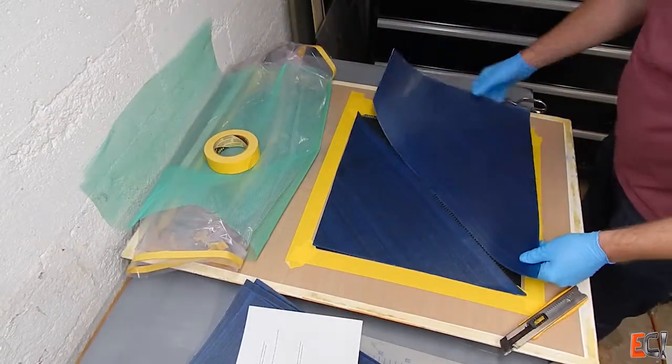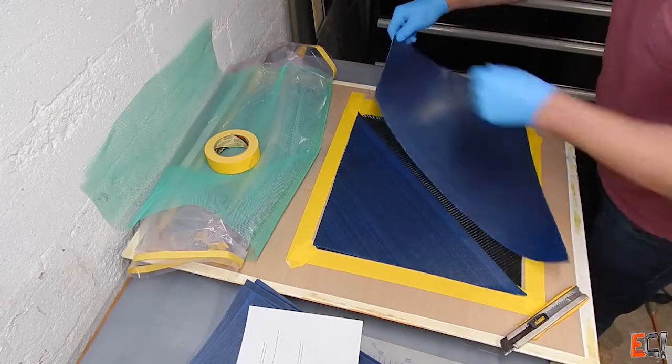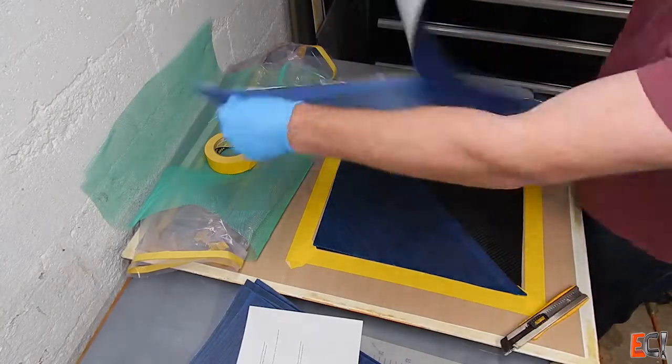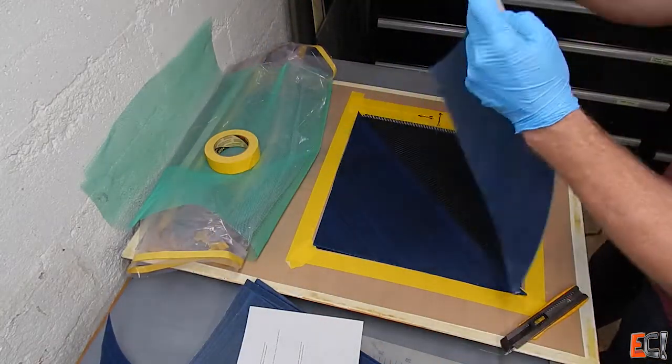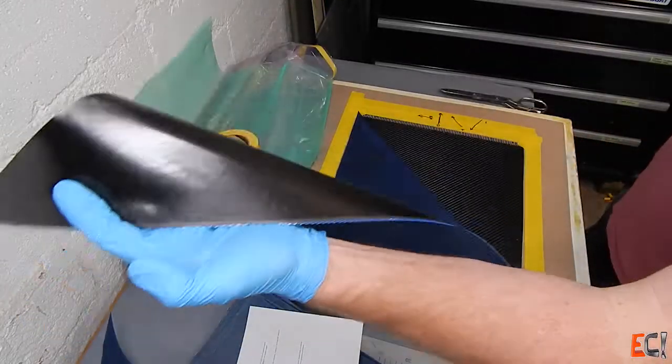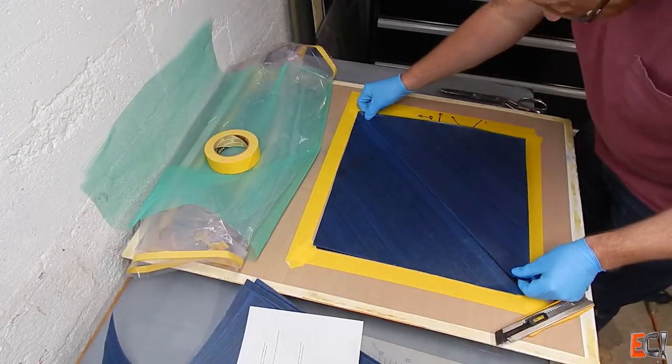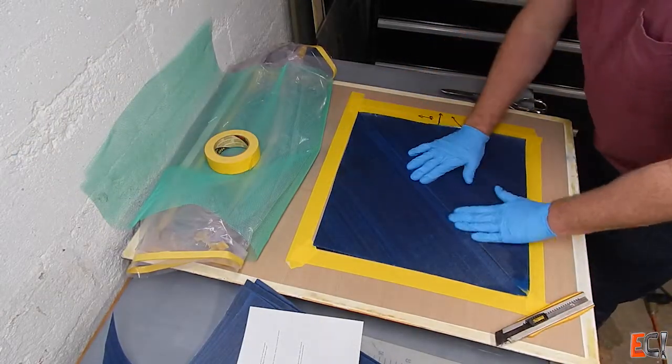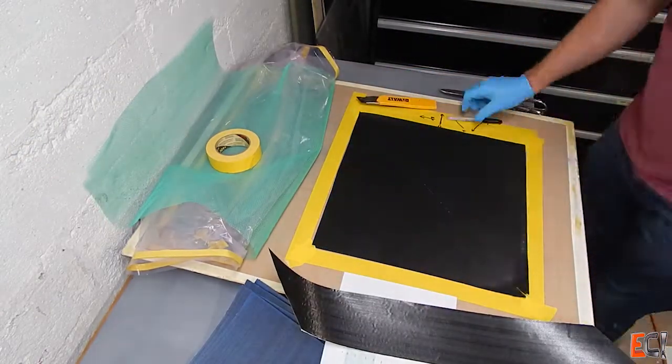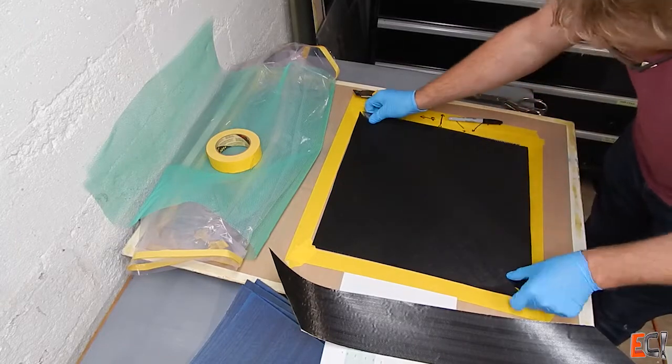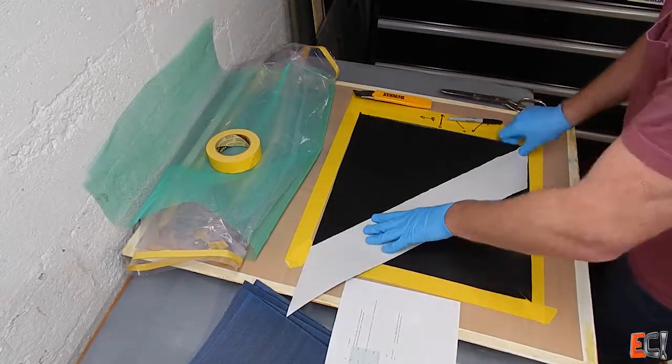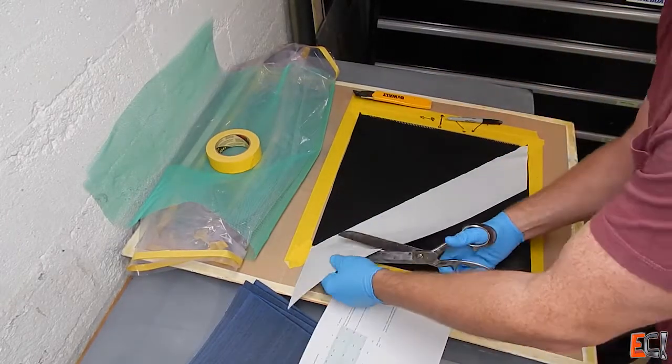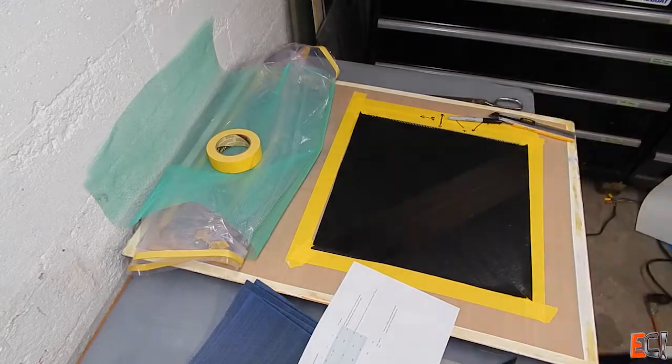Peel the backer and lay it down. I'm being pretty sloppy about the edge here and really focusing on the joint. What I did there I just tore the piece in half because this has got no stitching. This uni tears nicely and I'll just be careful to make sure that the joint is as tight as possible without any overlap.